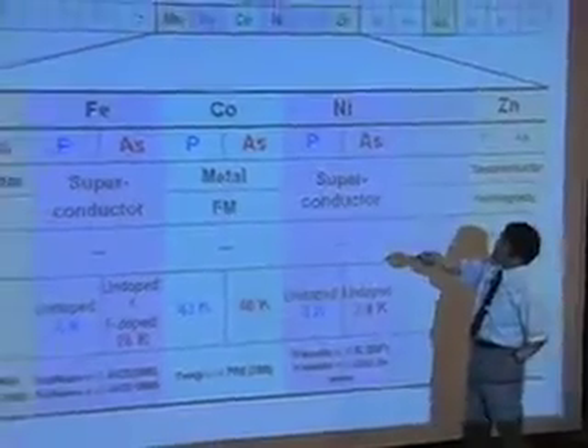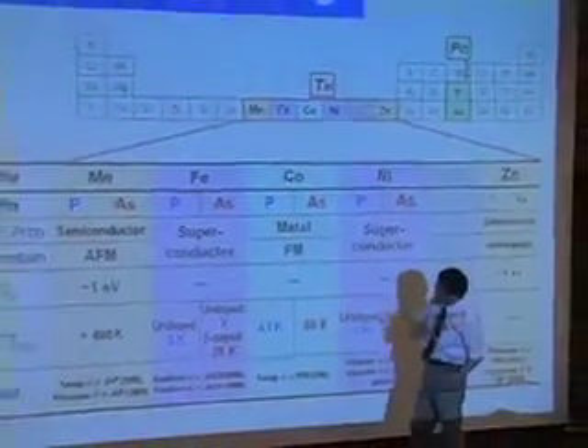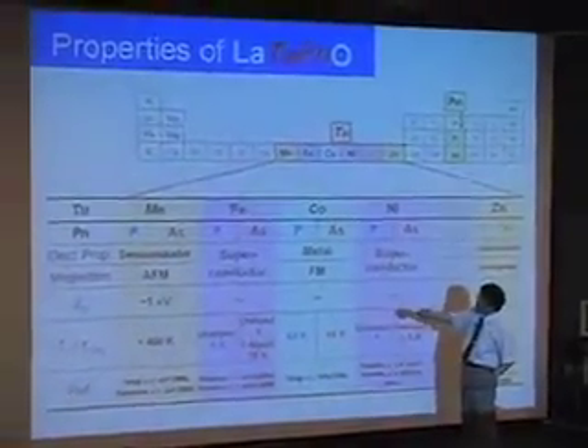So we synthesized these materials. From manganese to zinc, we synthesized lanthanum transition metal pnictide oxides. This is the result.